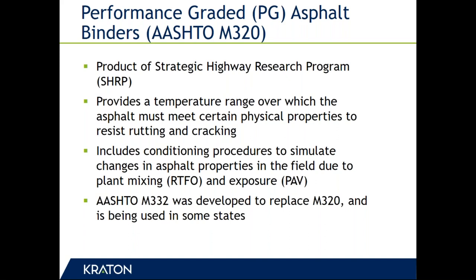At any rate, what the PG specification does, as opposed to the previous versions, is instead of basing things on a reference temperature, like for the viscosity test, 98.6 degrees Fahrenheit, for penetration, 77 Fahrenheit, which is around room temperature, or 25 degrees C, and for viscosity, 60 degrees Celsius or 140 Fahrenheit. What this does is it tests the asphalt binder at temperatures that are analogous to temperatures in the field, and the criteria have to be those which are related to performance in terms of resistance to rutting, low temperature cracking, and fatigue cracking in the field.